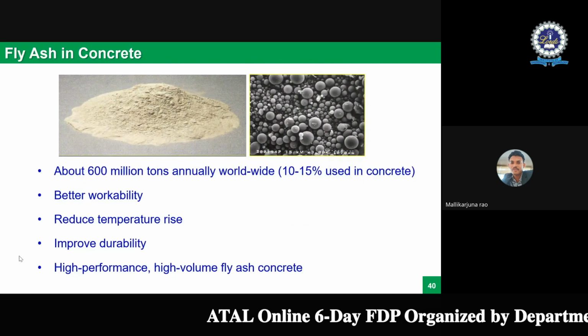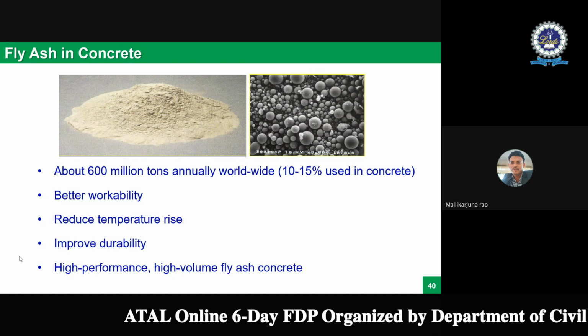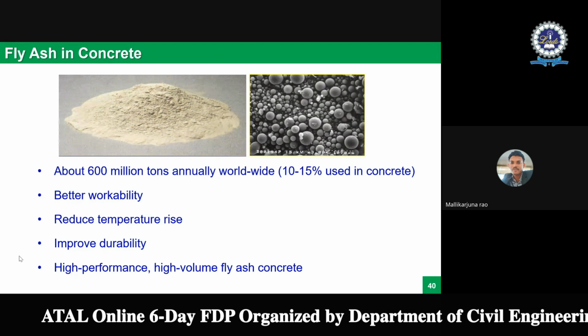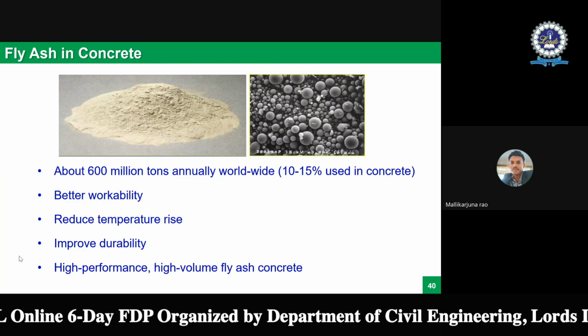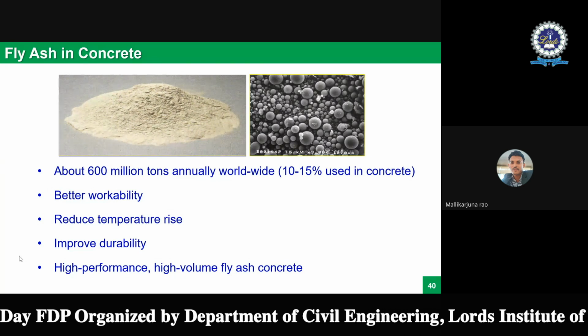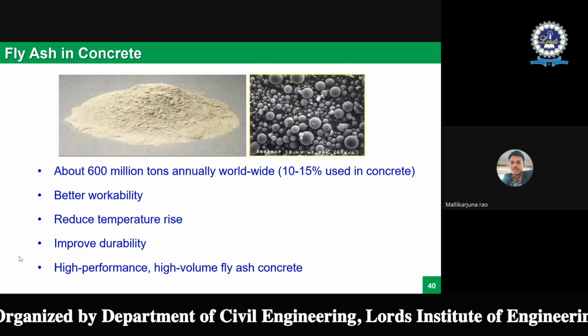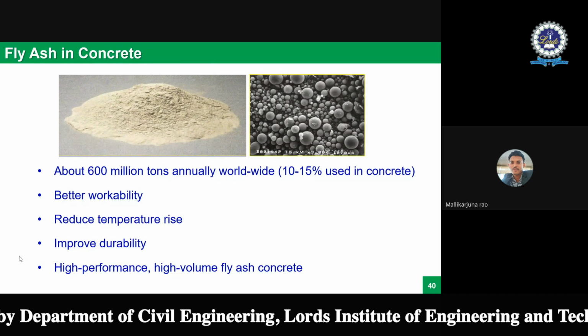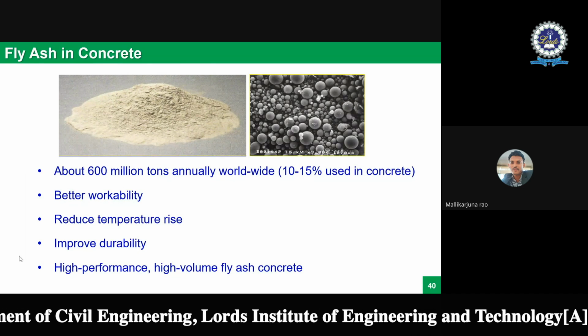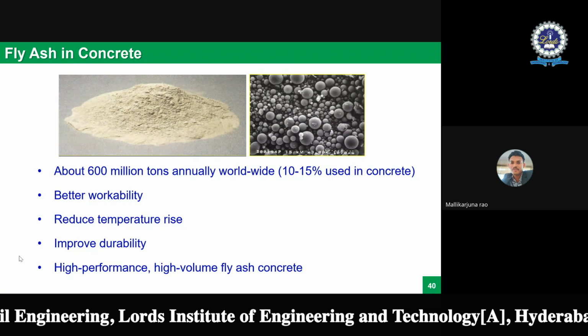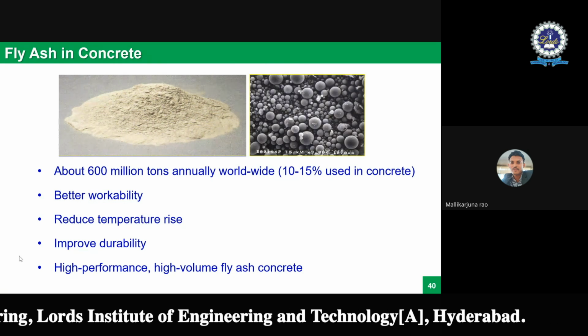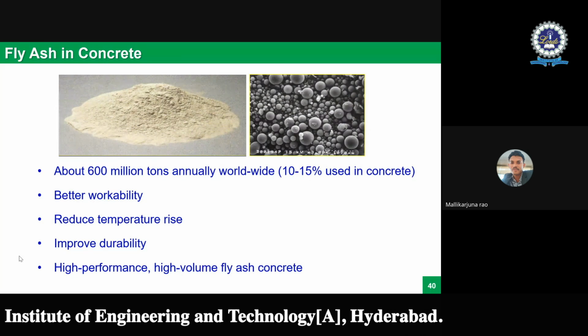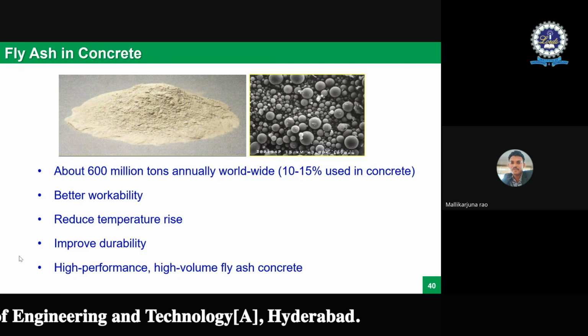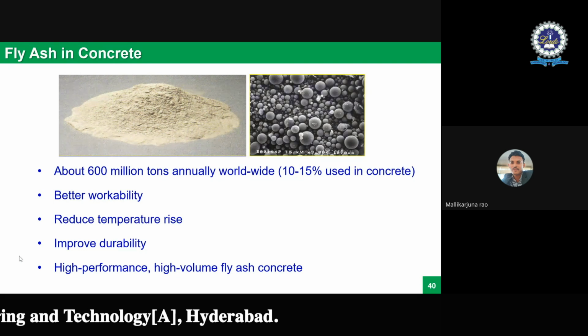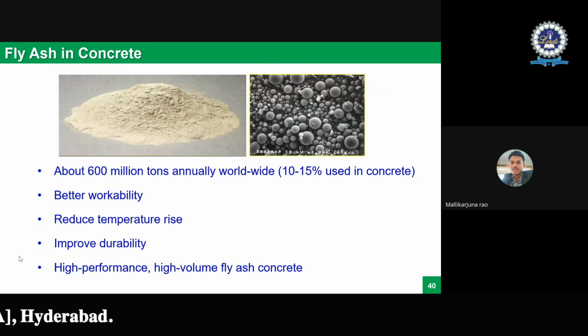Fly ash, everyone already knows that approximately 600 million tons are produced every year worldwide. Now we are using approximately 10 to 15% inside the concrete. In PPC also we can replace it with approximately 25 to 30%, where it will give you better durability. And the temperature rise that would happen will be reduced through your fly ash. The particle size of fly ash is smaller compared to cement particles, and it reacts with your calcium hydroxide. Again, the large quantum of silica present inside the fly ash will react with the calcium hydroxide and form calcium silicate hydrate gel.